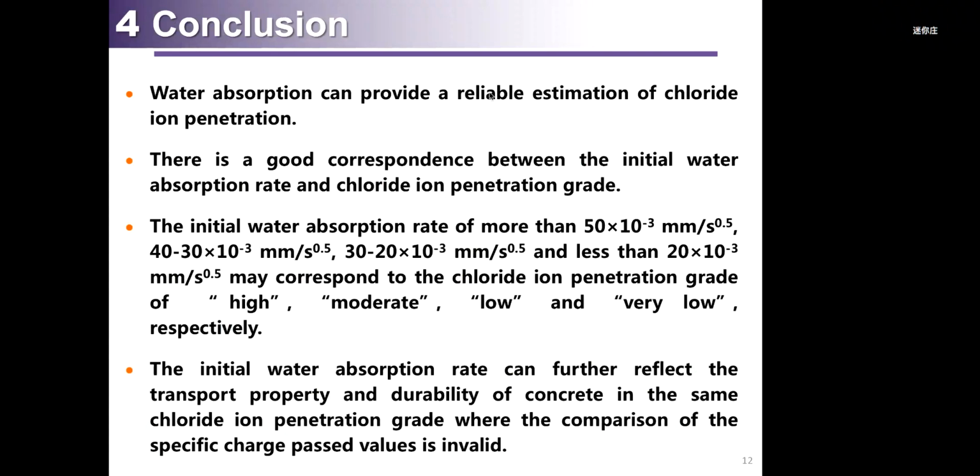The initial water absorption rate can further reflect the transport properties and durabilities of concrete in the same chloride ion penetration grade, where the comparison of the specific charge passed value is invalid.